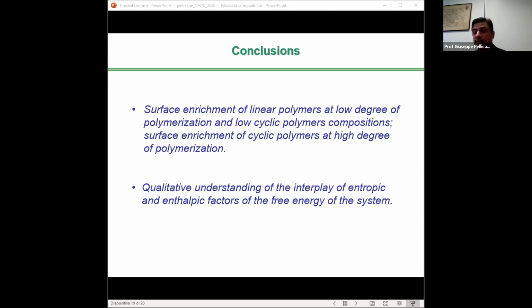On the contrary, when we consider long chains, we observe that cyclic polymers fold less than linear ones, so they lose less conformational entropy. So even if linear polymers can enhance the entropy of their chain ends, the entropy balance is likely to favor cyclic polymers at the interface. So the cyclic enhancement for long chain lengths emerges as a genuine entropic process, which is driven once again by the presence of the loop geometry, preventing cyclic chains at the interface from folding as efficiently as linear chains.